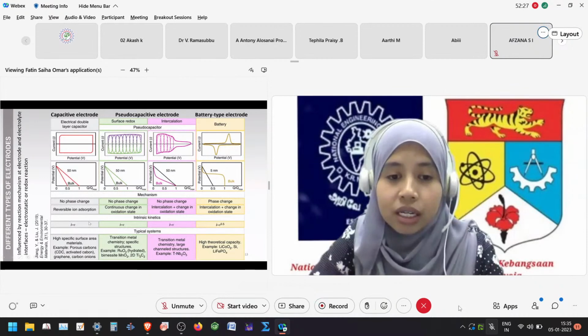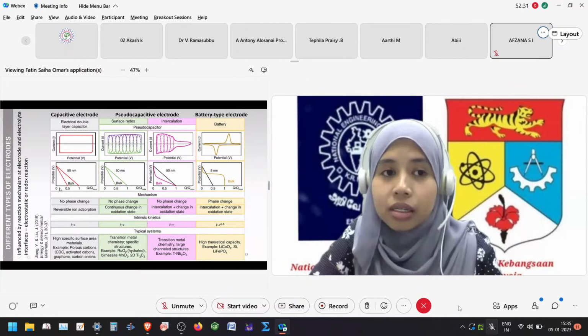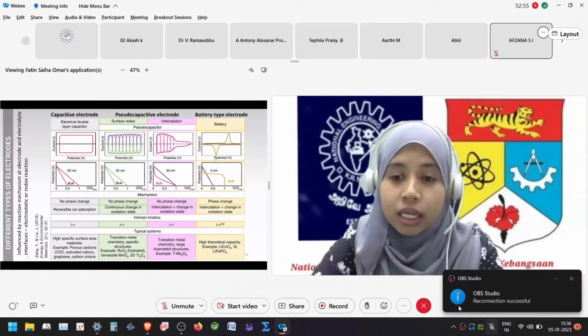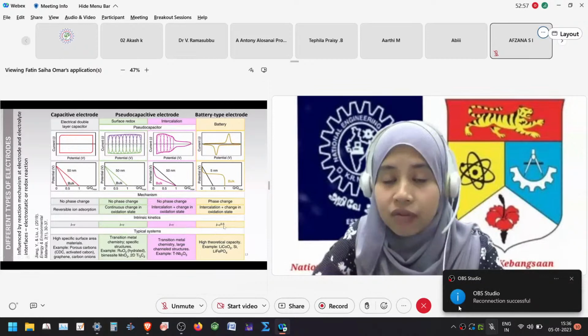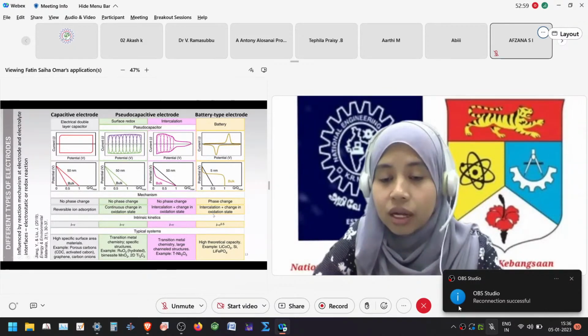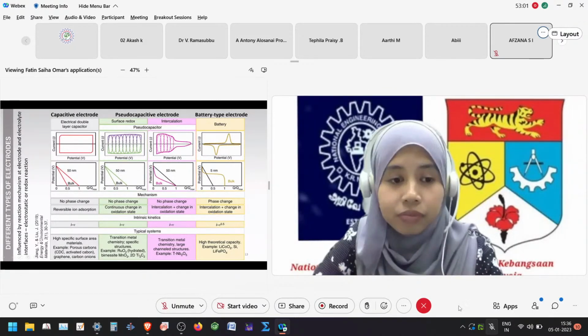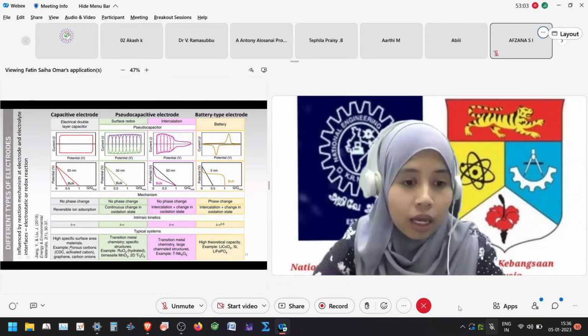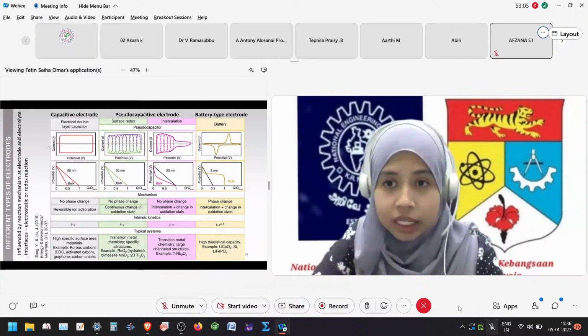So if the gradient is approximately 1, it means that it is a capacitive electrode or pseudocapacitive electrode. But if the gradient is 0.5, it is governed by diffusion. And below are examples of the material for each of the electrodes.